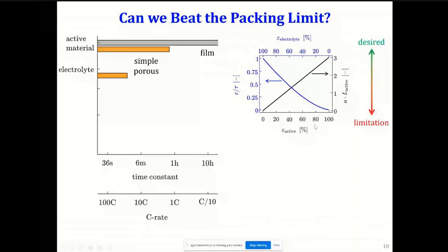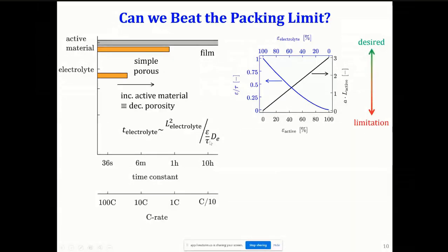Now, what would happen is, as you go to higher and higher active packing, you would be limited by transport, because you are now going into very low values of epsilon over tau. And recall that epsilon over tau, that constriction factor, comes in the denominator, so it will substantially increase the time scale you need to spend for lithium ion transport. And then it would make your electrodes more transport limited.